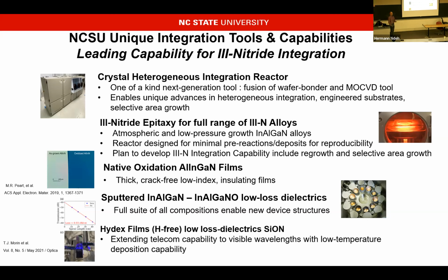One of the things that John Weir developed at Lehigh was the demonstration that you can oxidize indium aluminum nitride films. This is actually significant because prior to this, the ability to oxidize aluminum gallium nitride, because of the high stress, limited you to very thin oxides. In this case, you can get 1,000, maybe even more angstroms of oxide without stress and delamination and defects propagating. That again opens up new avenues that we can use to make better optical devices.